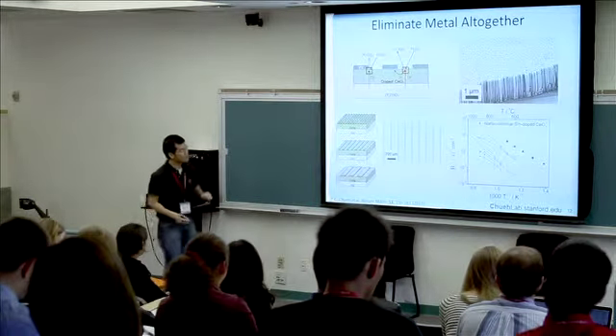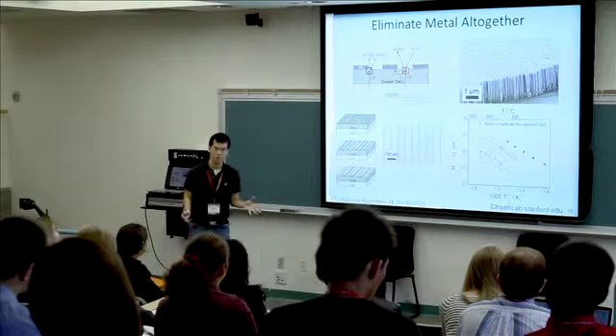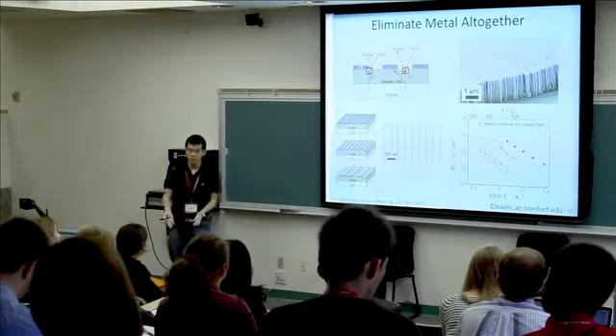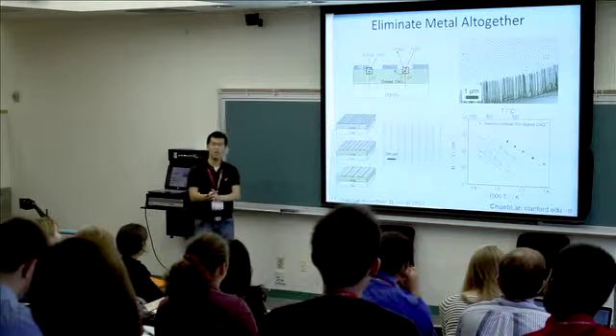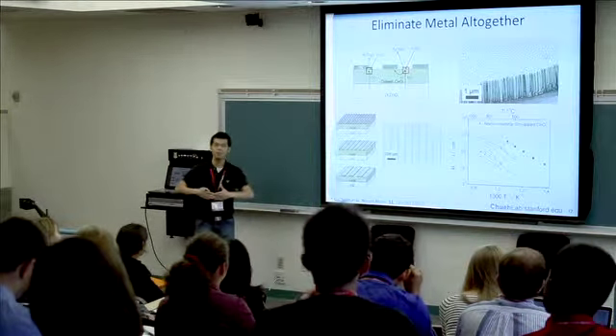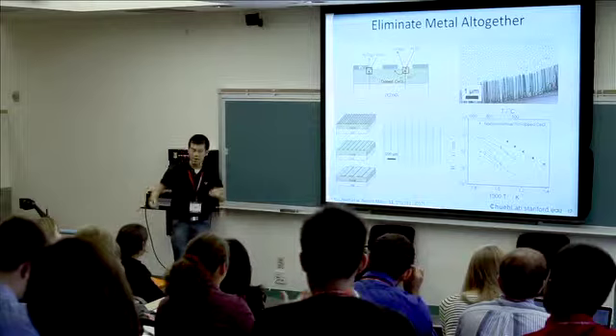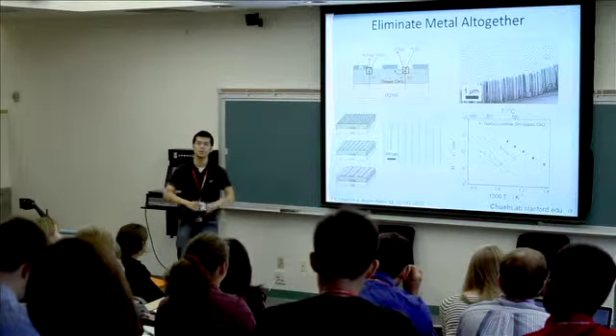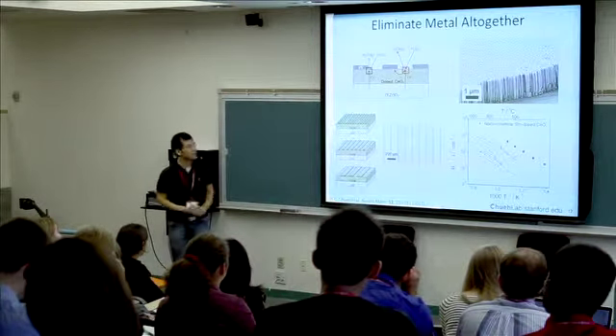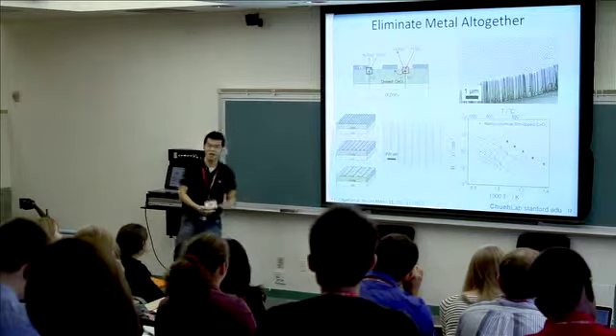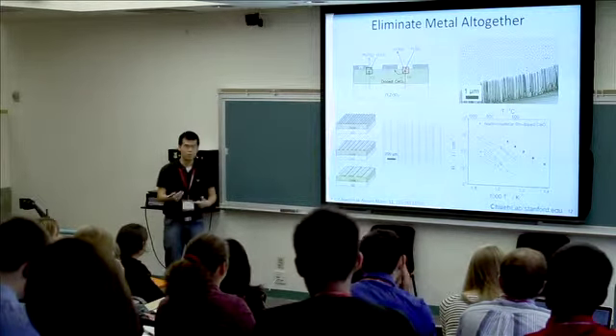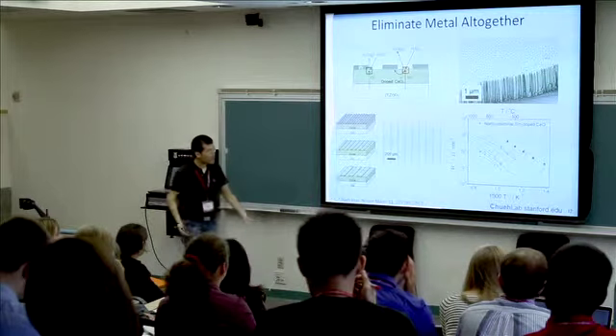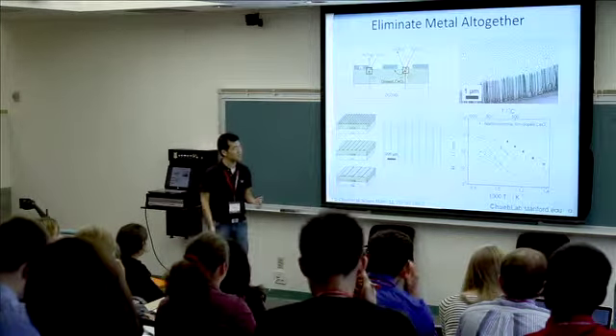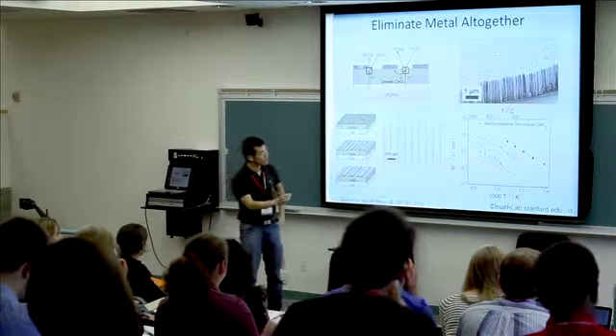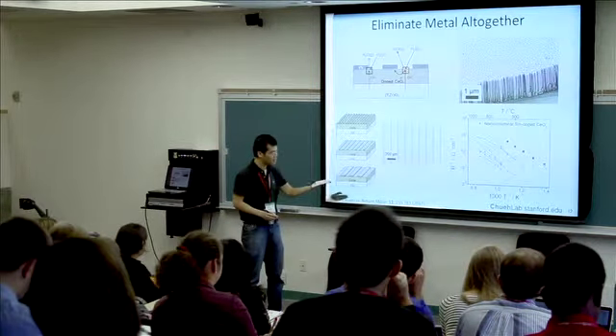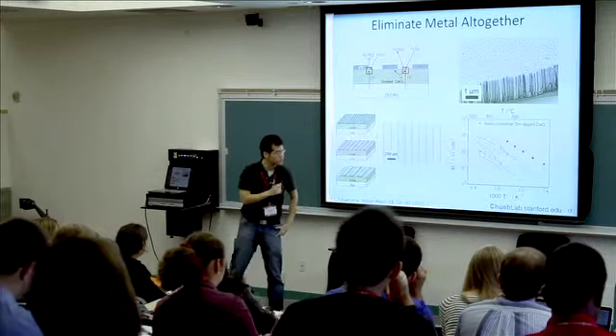So we actually made a very nice, elegant nanostructure from this. Typically in the past, for polymer electrolyte fuel cells, we tend to optimize the amount of surface area carried by the platinum. So we made really, really small platinum nanoparticles on the order of 10 nanometers or less. But it turns out that we can also do the reverse. Rather than optimizing the metal, we optimize the ceramic, the oxide. So we grew nanowires of cerium oxide, and we showed in this plot, on the y-axis is activity, higher is better, and the x-axis is inverse temperature.